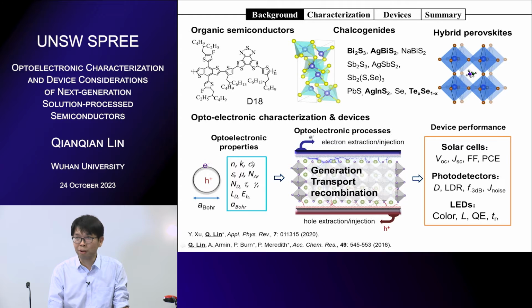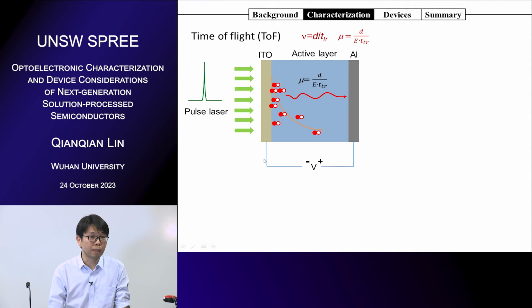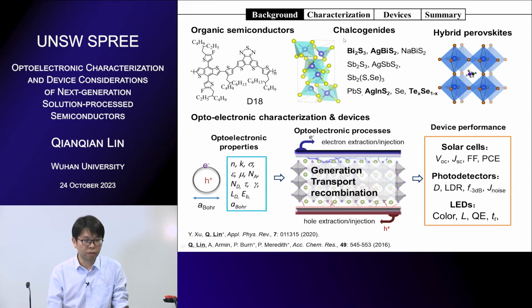We can get it from the textbook: we use the Hall effect. Classically, we use it for silicon, for very conductive semiconductors. But the Hall effect does have problems for solution processed materials. For organics and perovskites, the conductivity is so low, and the mobility is maybe 6-7 orders of magnitude lower than silicon. So it's very hard to use the Hall effect to measure the mobility of perovskites and organics. So we have to develop new techniques to measure mobility.